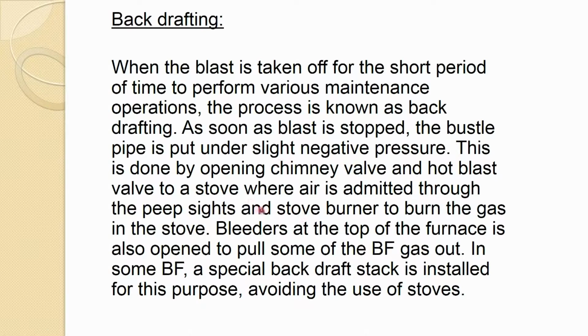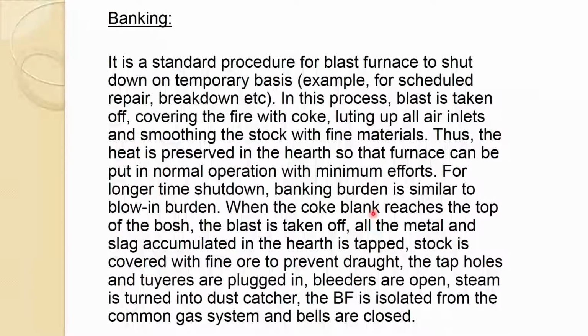Many terms which are used here, you have seen in those figures. So, I do not have to repeat; otherwise you can go look at the figures again. So in this one, actually, a negative pressure is put on the bustle pipe and stoves, and the gas is burned in the stove. Bleeders at the top of the furnace are also opened to pull some of the blast furnace gas out, and in some blast furnaces a special backdraft stack is installed for this purpose. If this is there, then you do not send it to stoves and you avoid the use of stoves. So, that is called backdrafting.